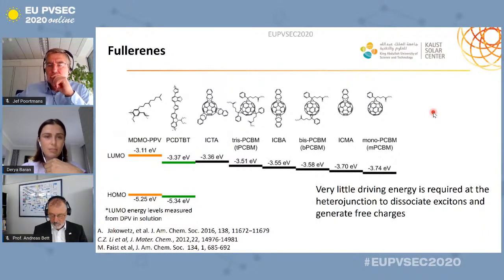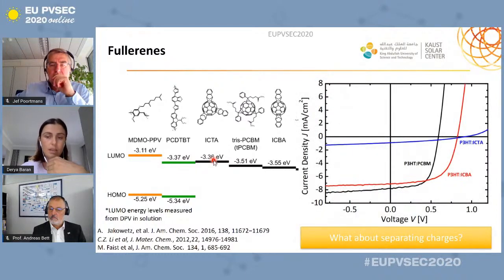So very briefly, I would like to give some credit to the workhorse fullerenes because they have answered a lot of questions in the OPV field. And we knew that very little driving energy is only required from the electron affinities with the fullerenes and the polymer to dissociate the excitons. But what was the limit was actually separating these charges into efficient solar cells. And there, although there have been several different types of fullerenes available, only very few of them worked very efficiently with several polymers, and ICBA was one of them, and it was very selective to the donor, actually.